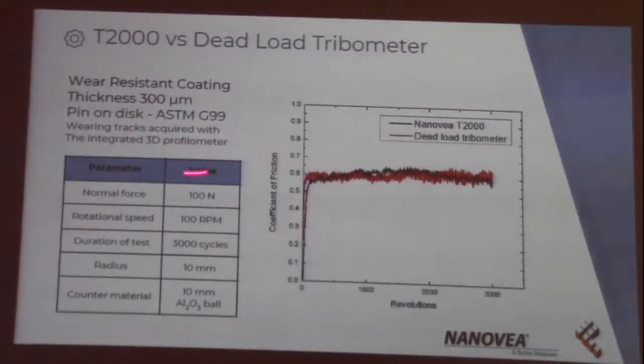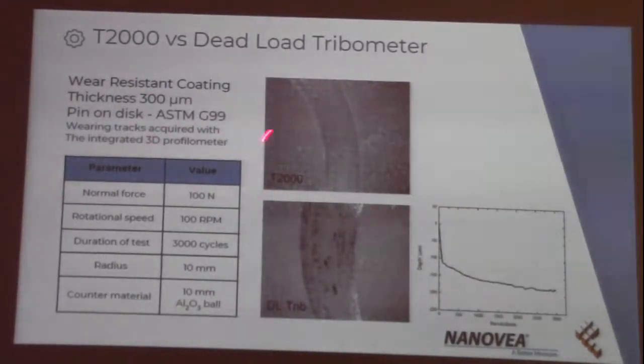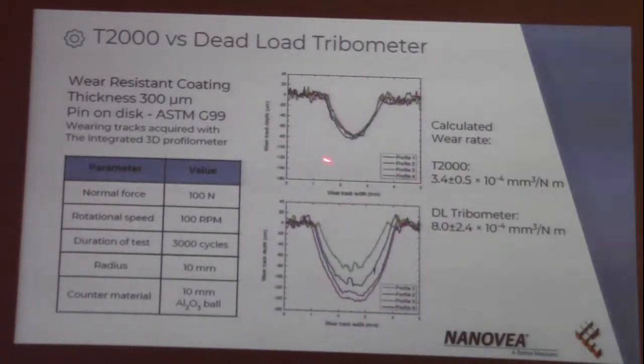microns, and under the ASTM G99, which is a pin-on-disc test with a precise norm, we did a test in comparison with the standard dead load tribometer. So the main fact is that, regarding the standard test, we have less noise and more or less the same behavior. But if we look at the surface and the fatigue that occurs, we can see that we have a smoother response of the surface, and also if we perform a 3D reconstruction, we can see